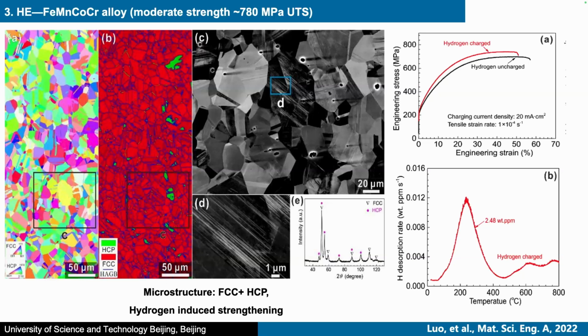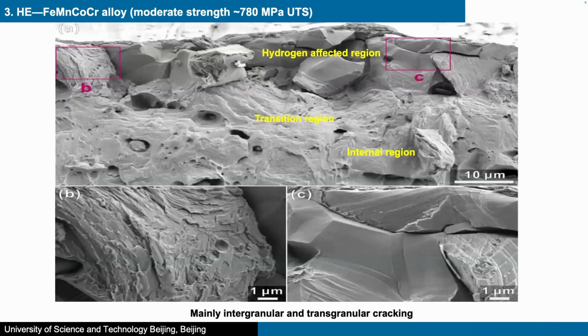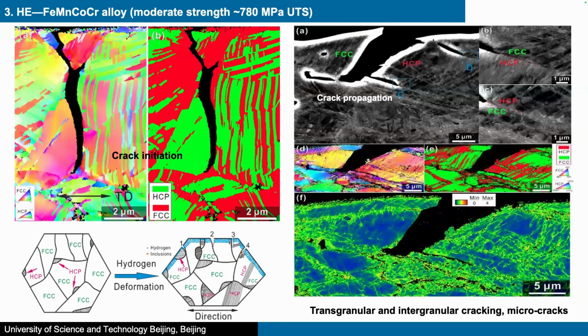And we did a similar experiment, and we found a slightly hydrogen enhanced strengthening observed in this type of alloys. And also we observed the fracture surface and found the hydrogen affected region was intergranular cracking, and also some transgranular cracking observed in the fracture morphology. And also we used the EBSD and ECCI to observe the crack initiation and progression.